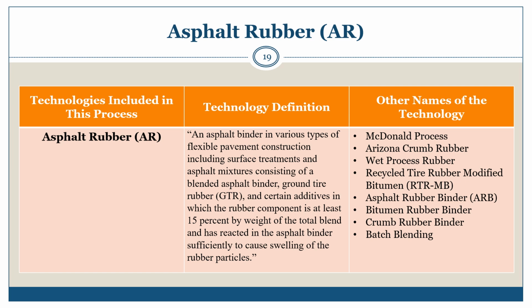Asphalt rubber, or AR, is defined here as an asphalt binder in various types of flexible pavement construction, including surface treatments and asphalt mixtures, consisting of blending asphalt binder, ground tire rubber, and certain additives in which the rubber component is at least 15% by weight of the total blend and has reacted in the asphalt binder sufficiently to cause swelling of the rubber particles. Other names for this technology include, with appropriate acronyms, the McDonald process, Arizona Crumb Rubber, wet process rubber, recycled tire rubber modified bitumen, asphalt rubber binder, bitumen rubber binder, Crumb Rubber Binder, and batch blending.